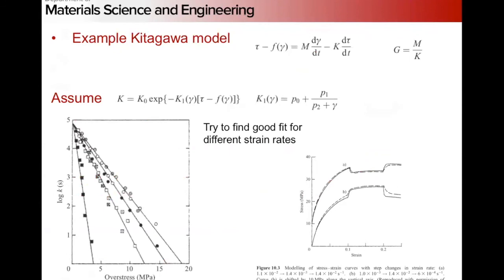rate tests, right, where you change the strain rate in the middle of the tests and look at how the stress changes. And this is sort of a very difficult test to try and capture, right? But basically, there's a huge number of assumptions here, right? We just sort of pick the form for how we're going to handle the stress response. We pick the form for one of the two constants and then solve for the other, right? So that's the differential approach.